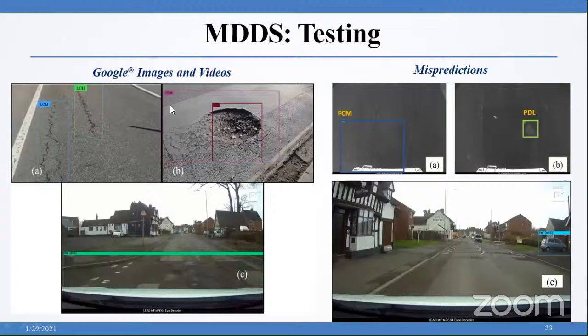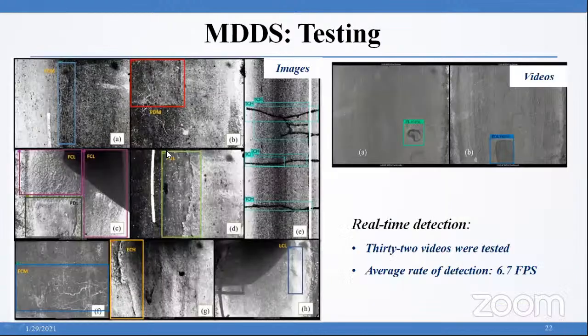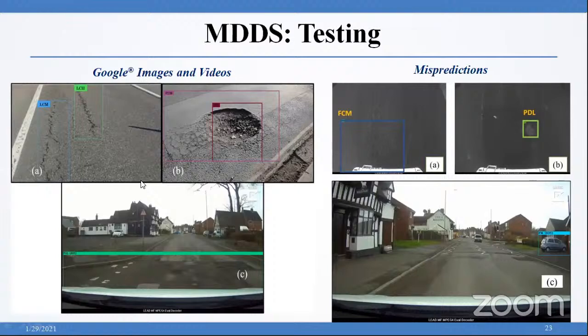The orientation of the camera was different. As you can observe in these 2 images, the orientation of the camera was different from the one which we used for training the system, and the image resolution was quite different from the ones used in the training of the system. Even though the camera orientation and the image resolution were different, the system detected the distresses as LCM and LCH appropriately in this particular case.